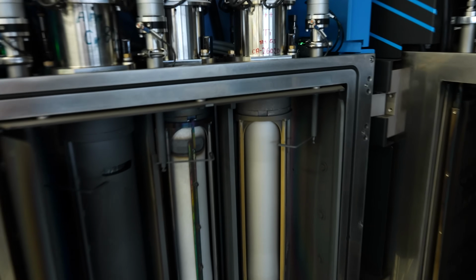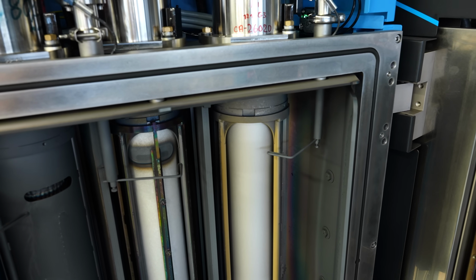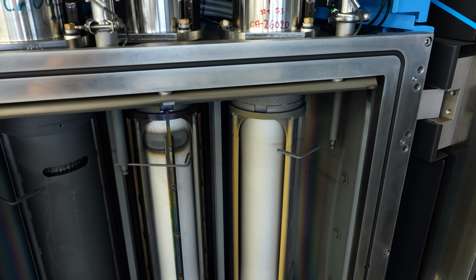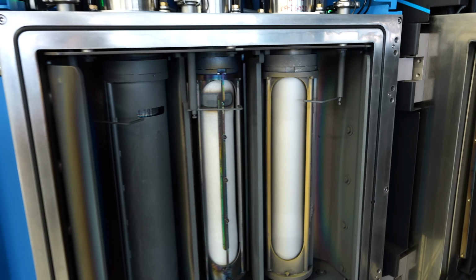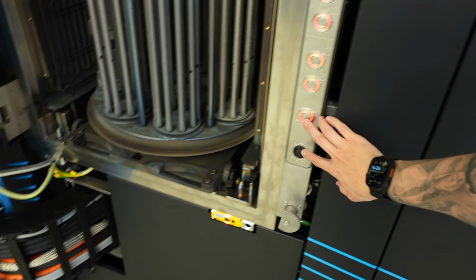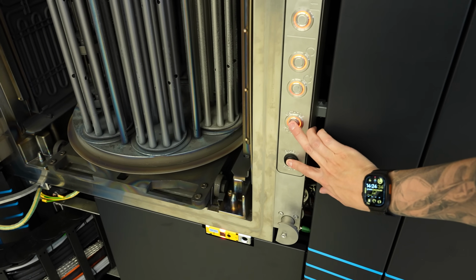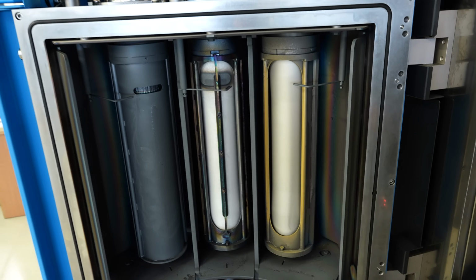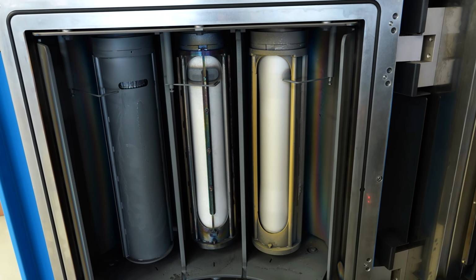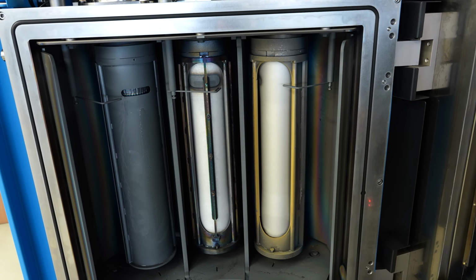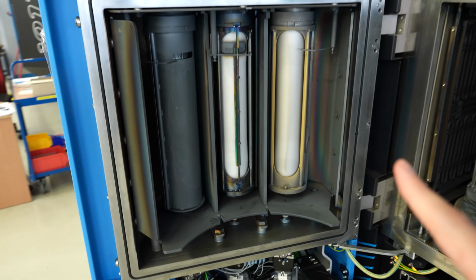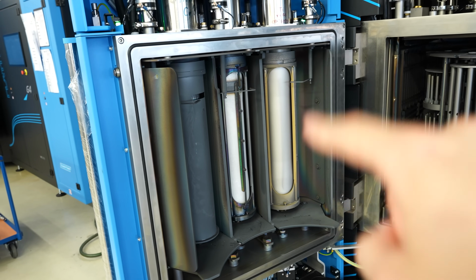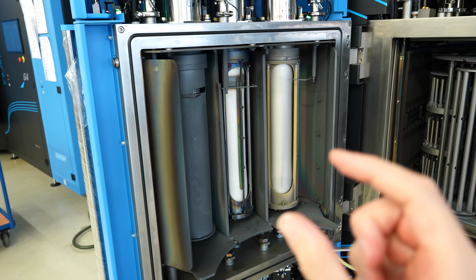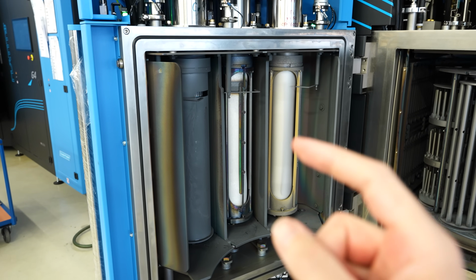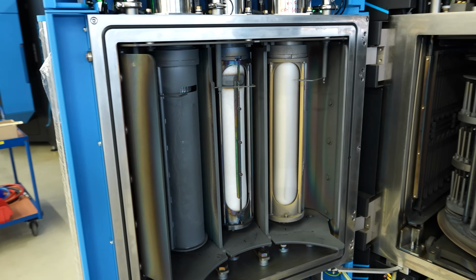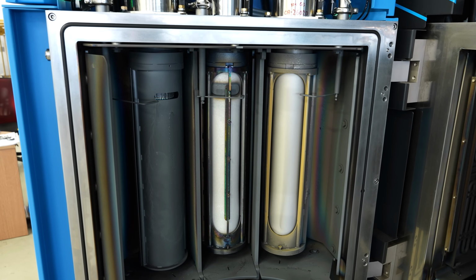And just going back to this, I want to show the arm that is igniting the arc on the surface. Another thing that's super cool about this machine: if I touch these buttons, the cathode is rotating, as you can see. That is also a very unique feature about this machine, because this arc is not constantly hitting the same area on a simple target, but because it's rotating, it is hitting basically the entire rod. And that has a huge impact on the quality of the coating that you're creating.